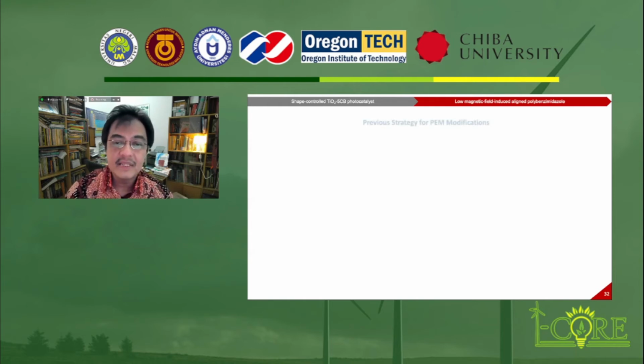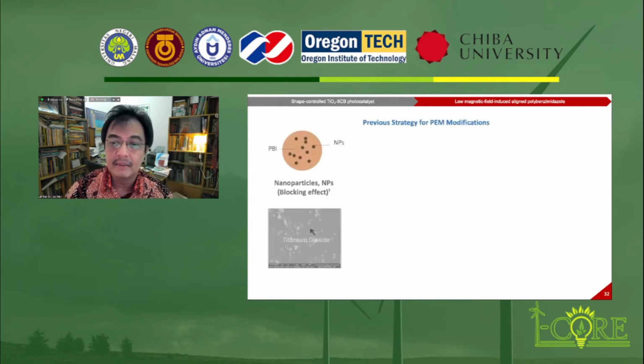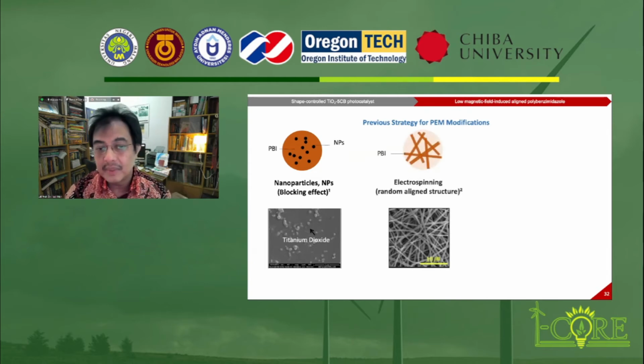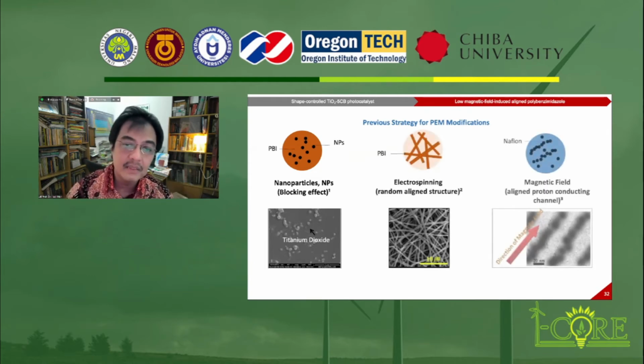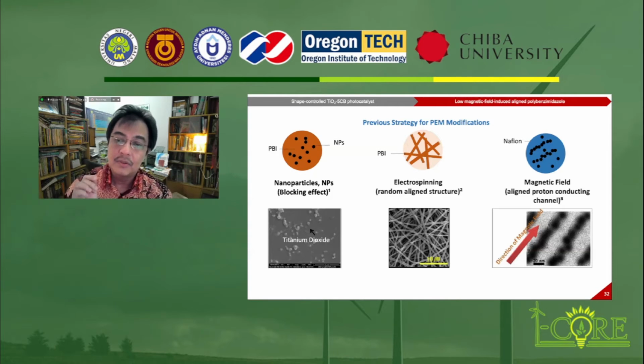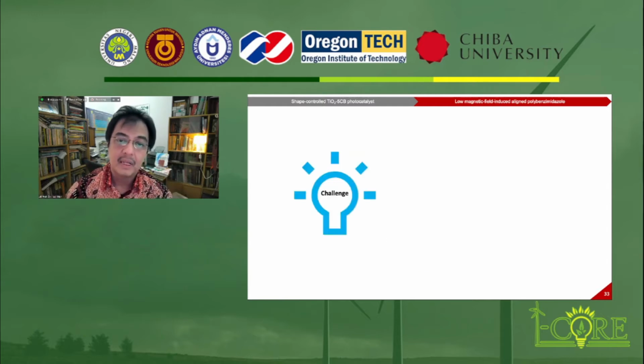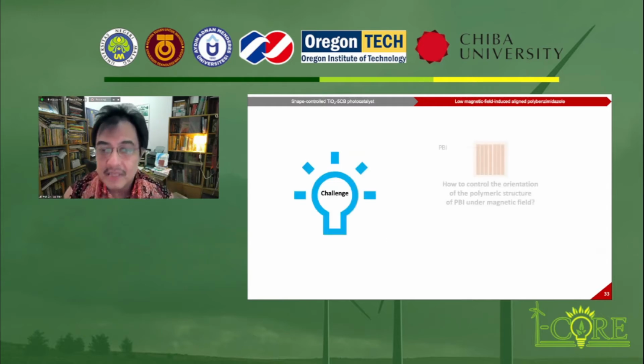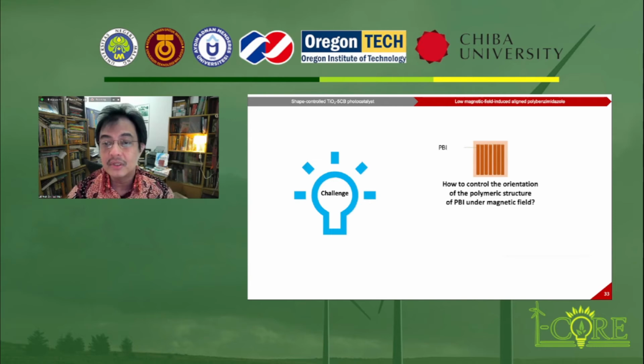To increase the efficiency of the proton exchange membrane, several strategies have been carried out. Among them is adding nanoparticles and also using electrospinning to produce a randomly aligned structure. One interesting method is to use particles that can align with the magnetic field, so that the proton conductivity increases. In this study, we use polybenzimidazole, a material that is considered a potential proton exchange membrane.